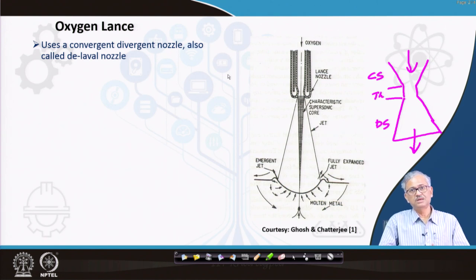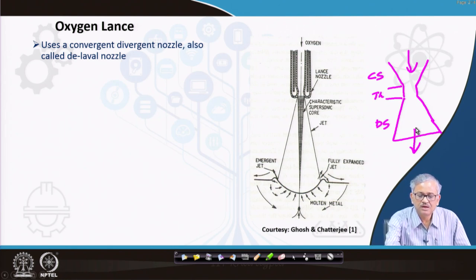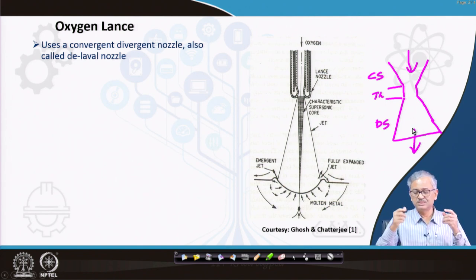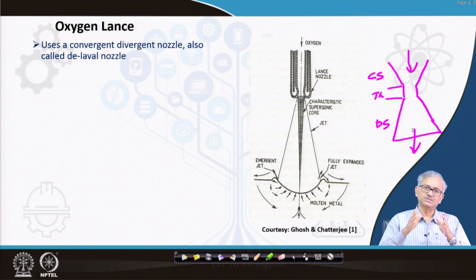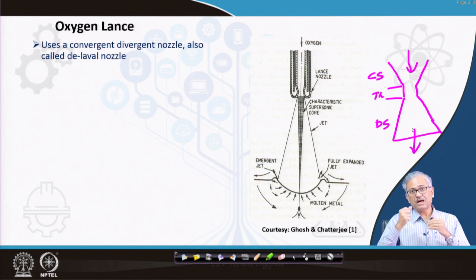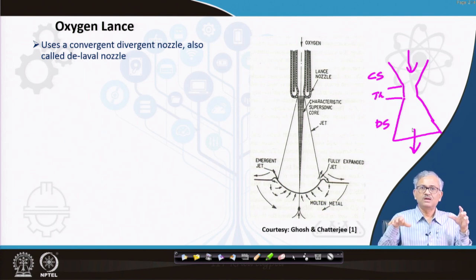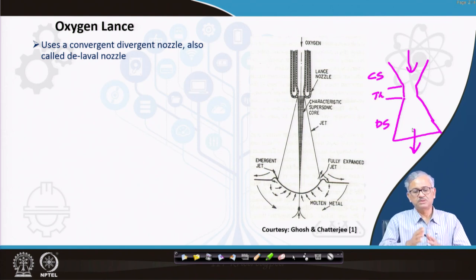But in the case of the convergent divergent nozzle, because of this design, the pressure of the oxygen when it is coming out of the diverging section can be controlled to one atmospheric pressure, by proper design of the divergent section length and all these things. You can get a very high speed oxygen jet emerging from the nozzle at atmospheric pressure. As a result, it will not interact with the ambient air, and the oxygen will travel with the same speed, at supersonic speed. So a supersonic jet will come out at around one atmospheric pressure.